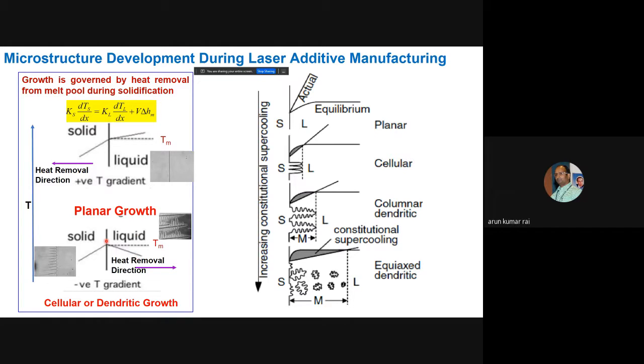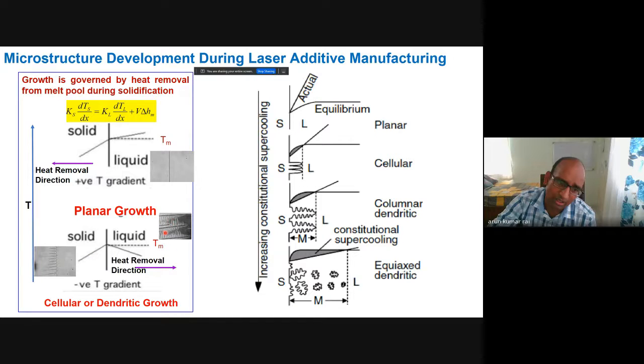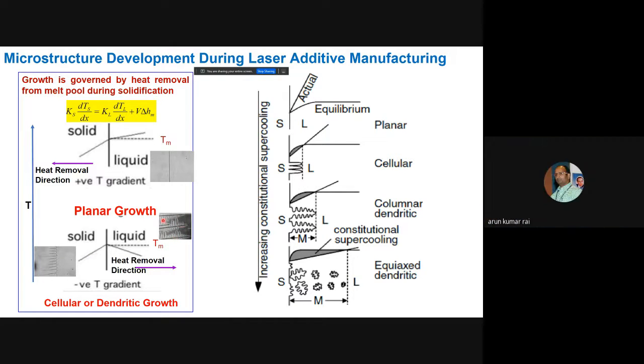In that scenario, what will happen? Your liquid will see a lower temperature than the solid. So my heat removal will start happening from the liquid side, and under that condition, the straight interface will not form. Protrusions will start forming in the metal liquid, and they will actually be stable. These protrusions will keep on growing to form a solid. So this kind of cooling leads to the formation of a dendritic structure, or dendrites you can say. These are dendrites or columnar dendrites. So many things will happen, and this happens because of the cooling rate.